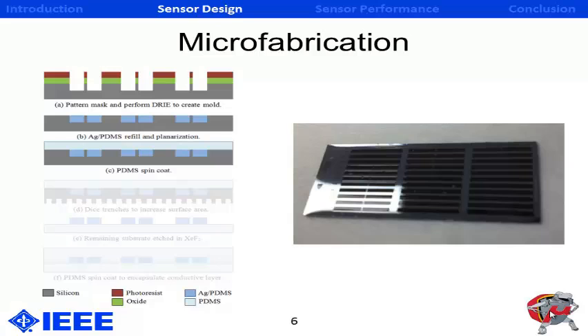Okay, so onto the microfabrication. It's done on a bare silicon wafer. First, it's masked and patterned, and a deep reactive ion etch is conducted down to 100 microns, as you see on the right. What you're looking at are pairs of electrodes, and these are in plane to the silicon wafer. Next, it's refilled with a conductive polymer. This polymer, we chose silver nanopowder and PDMS. In this case, the silver nanopowder had a particle size of 80 to 100 nanometers. It was at 72 weight percent. It's refilled and planarized, and then a layer of PDMS is spin-coated.